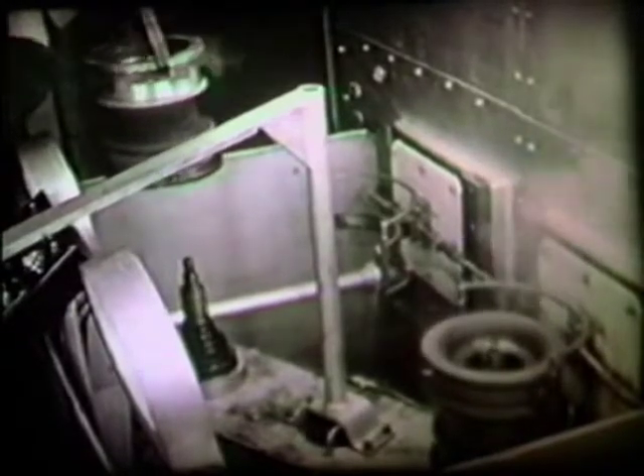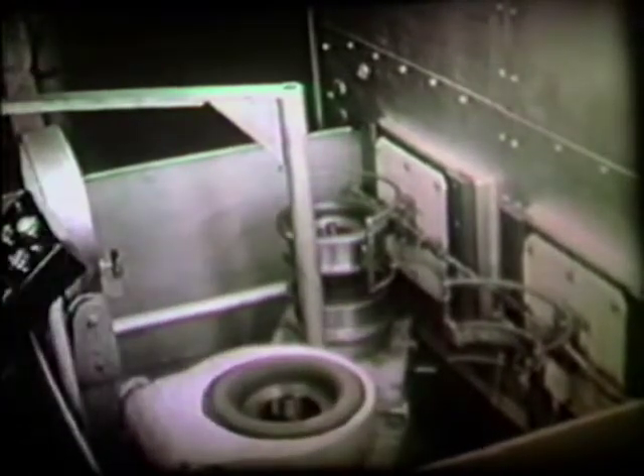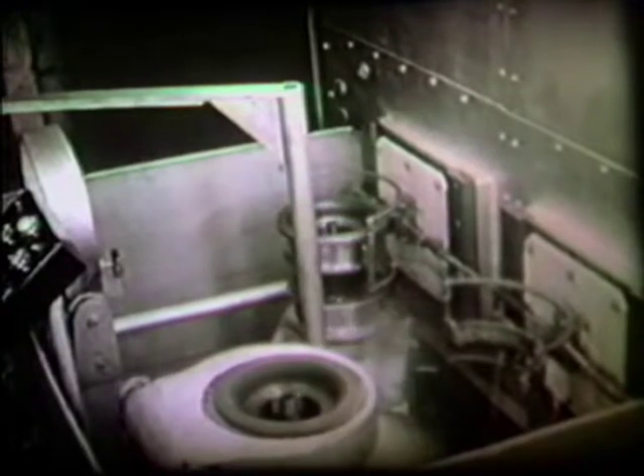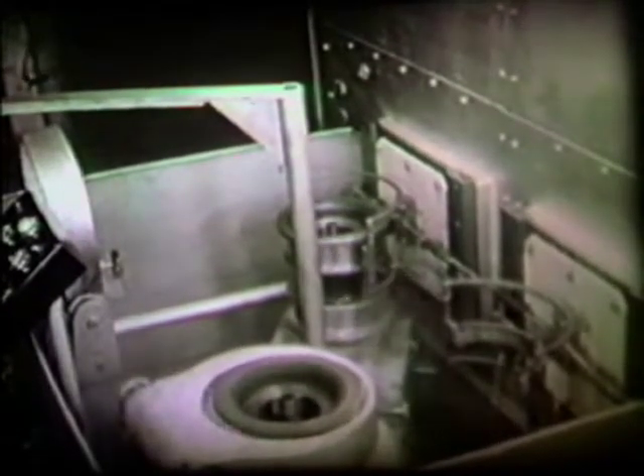Now this is the most important part of the whole process. Instead of producing these rollers from expensive alloy steels, we use a 0.4 to 0.5 carbon steel and high-frequency harden to any given depth. This roller will have a 3/8 of an inch hardened case on it, which will give a hardness of Rockwell C60, far superior to all those other fancy steels which our competitors are compelled to use through lack of this plant. This workstation was designed and built by the staff of Tractor Spares Limited.